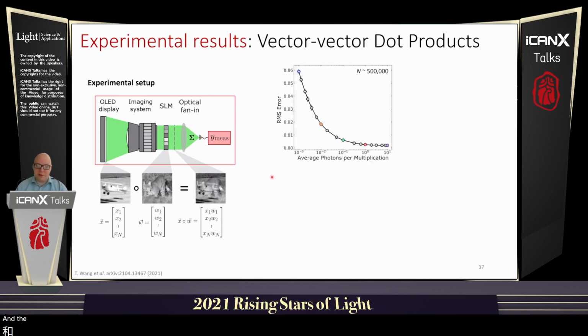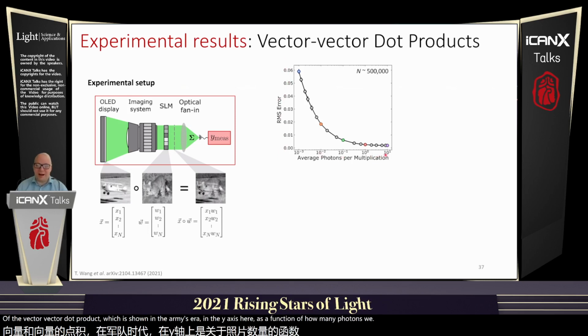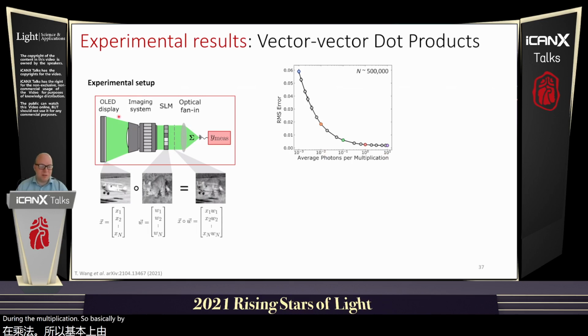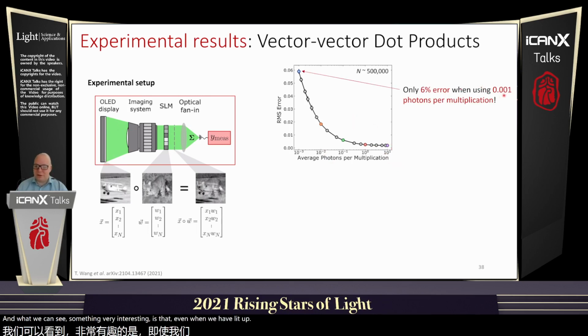And the experiment that we performed was characterizing the accuracy of the output of the vector-vector dot product, which is shown in the RMS error on the y-axis here, as a function of how many photons we allowed ourselves to use during the multiplication. So basically by modulating the intensity of the light source. And what we can see is something very interesting: even when we have a thousandth of a photon on average per multiplication, which is all the way on the left side of the graph here, the error that we have is only 6%.